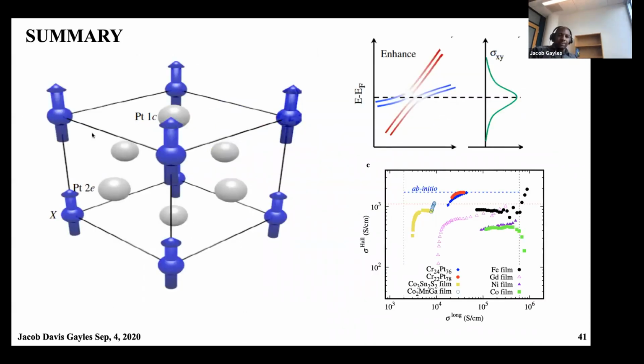So in summary, we discussed this cubic compound, chromium platinum 3, which gets distorted from the magnetic symmetry group to be tetragonal, and shows this enhancement of the Berry curvature for the anomalous Hall effect, which is clearly shown from the experiment and in theory.